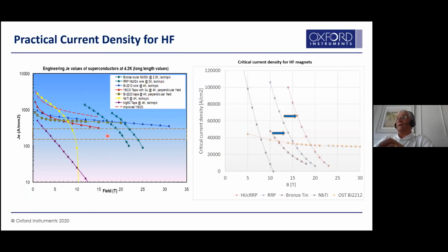So one of the critical elements to think about is which wire to select for these high field systems. There are over 4,000 superconducting materials being researched and developed across different labs in the world, but really 6 of them are of practical use. Here I'm showing the engineering current density. If you are talking about up to 10 Tesla, this yellow one corresponds to niobium titanium. Our interest in design, this dashed box, corresponds to the region where we would like these coils to be developed. So up to 10 Tesla, you can see the favorite will be niobium titanium.